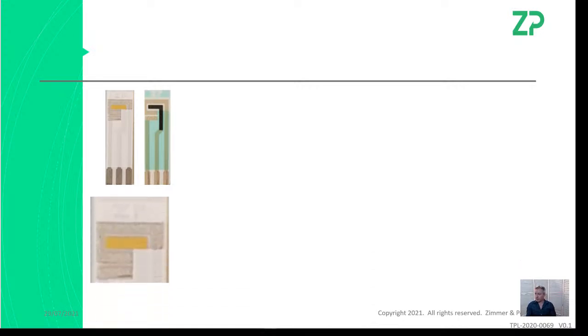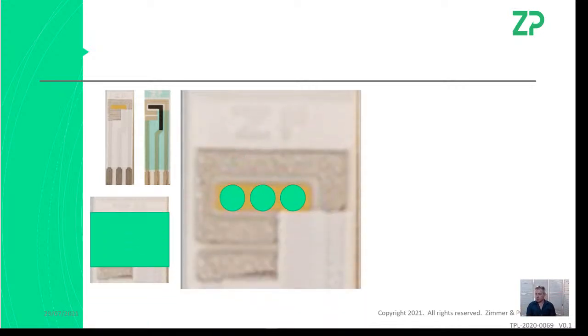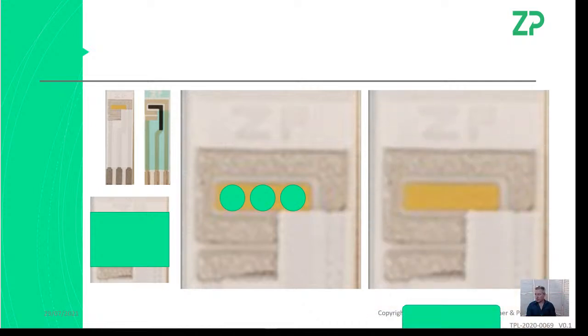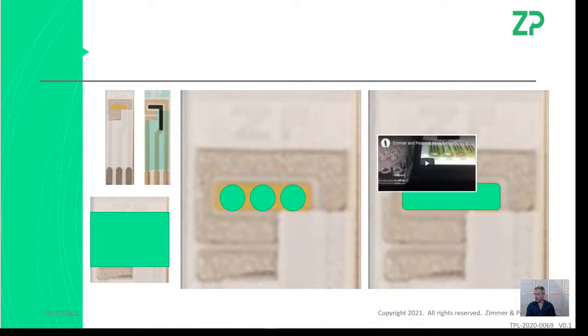Now, what I suggest is that, whenever you've got the carbon electrode, the gold electrodes, don't flood the electrodes with your reagents. I suggest that you just put 3 dots along the electrode like this, and then just spread it with a pipette tip and cover it that way. So if you're having a problem with irreproducibility, then I would suggest that you need to get that deposition pretty reproducible. So please do it the way I've just suggested, that you don't spread it over everything. 3 dots, and then just drag the pipette tip and merge the 3 dots that way.